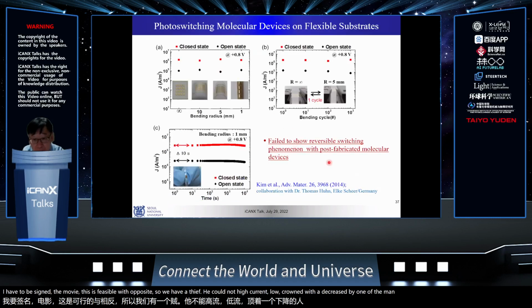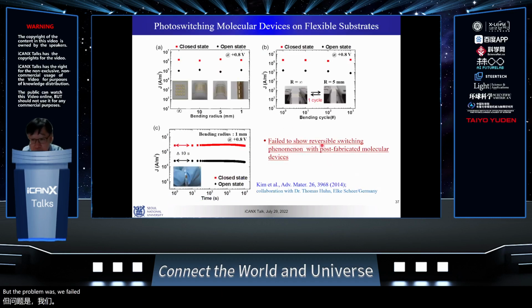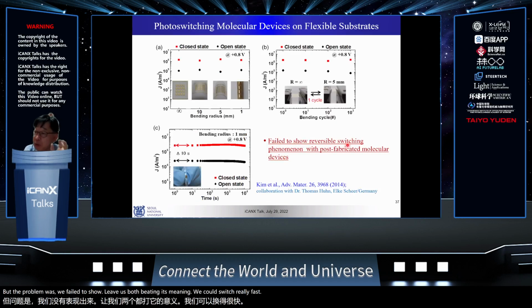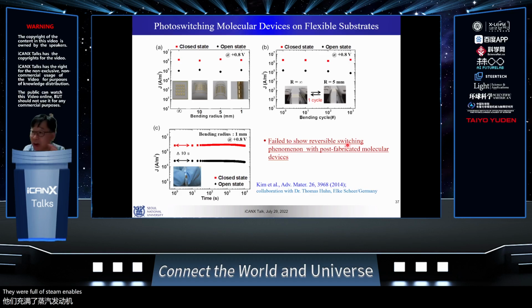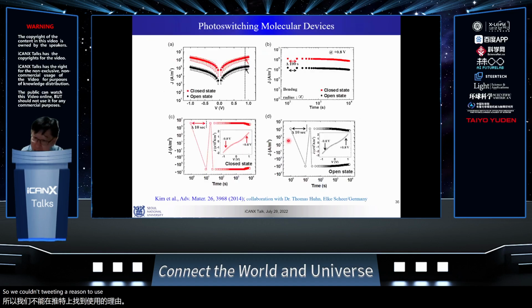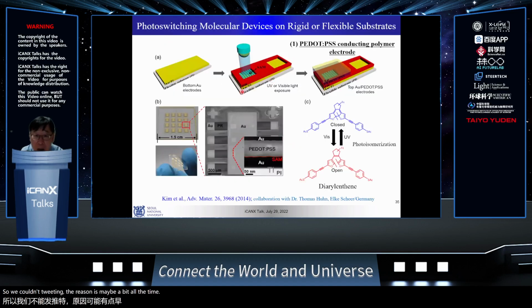But the problem was we failed to show reversible switching, which means we couldn't really switch, but it remained as on state or off state, depending on whether we fabricated the device in a UV environment or a visible environment. So it remained as it was. So we couldn't switch it. The reason is maybe at that early time, our power was not enough, or the overall transmission of the light was not enough. The energy was not enough to give to this reaction.